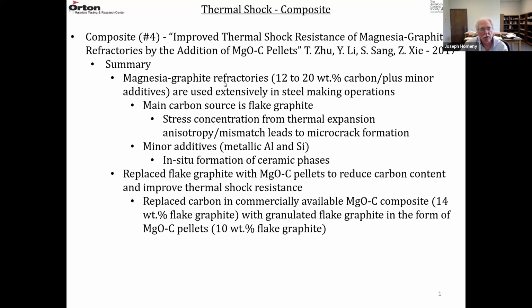So these magnesia graphite refractories are usually 12 to 20 weight% carbon, and then the minor additives like the antioxidation agents. And these are used extensively in steelmaking, basic oxygen furnaces, ladles, electric arc furnaces. The main carbon source is typically flake graphite, has a little better oxidation resistance compared to amorphous carbon. And there's a stress concentration from the thermal anisotropy of graphite, and that mismatch creates microcracks.